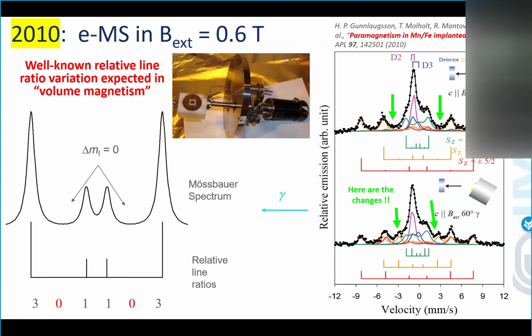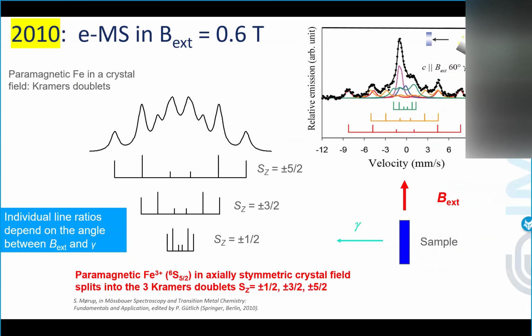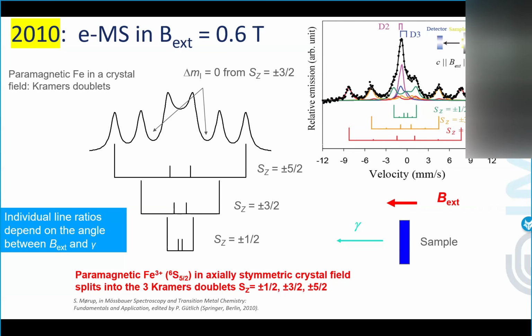And in this fit, actually, 3 separate Kramers doublets were used that were nicely following the angular dependence that was expected. So this comes from slowly relaxing paramagnetic centers. Going down to theory, there is a nice chapter by Mørup in the Philipp Gütlich book that was very instructive. If you have paramagnetic iron in an axially symmetric crystal field, and this happens only for the 3+ because of the symmetry, since it is spherical, then from a more complicated Hamiltonian you have these 3 separate Kramers doublets, which separately follow the angular dependence. And by using this analysis, we found that at the end we were dealing with slowly relaxing paramagnetic centers.